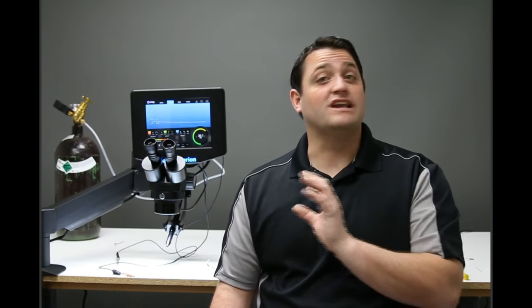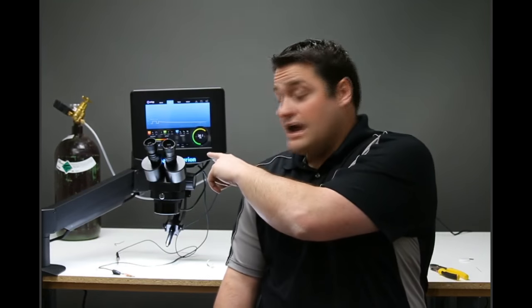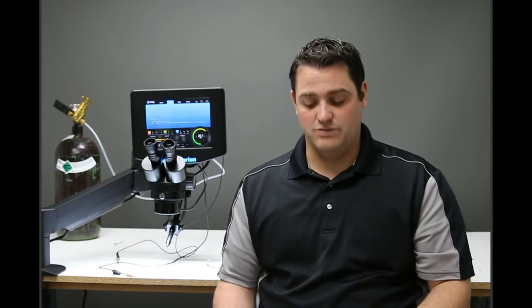Today I've got my gas turned up a little bit high, and you'll hear it in the video, but the main purpose of that is so that you can hear the gas flowing and know that we've got that argon. You can see the tank over here by the side. That's extremely important to get good welds, to get a stable arc, and very important when working with silver. So we definitely recommend using argon in all of your welds, but specifically as we weld with silver today.